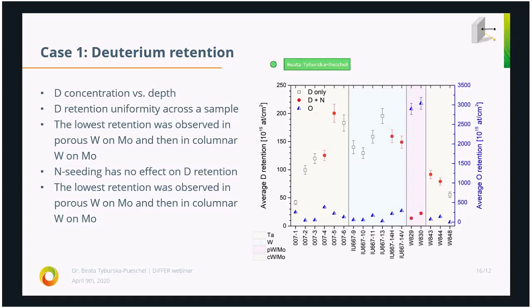So what you see on this plot, you have average deuterium retention from each sample, and here are the different sample names. They form 4 groups. Here the yellow group is tungsten on tantalum substrate. The blue group is the pure tungsten. The pink group is the porous tungsten on molybdenum substrate, and then we have the green group, which is the columnar tungsten on molybdenum substrate.